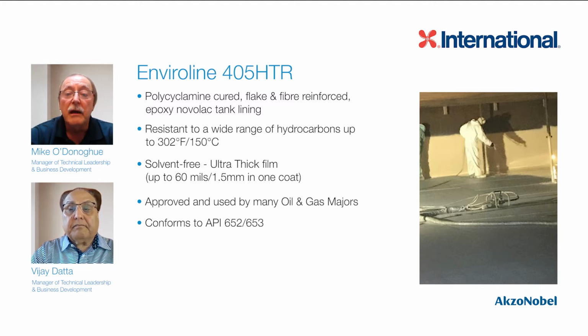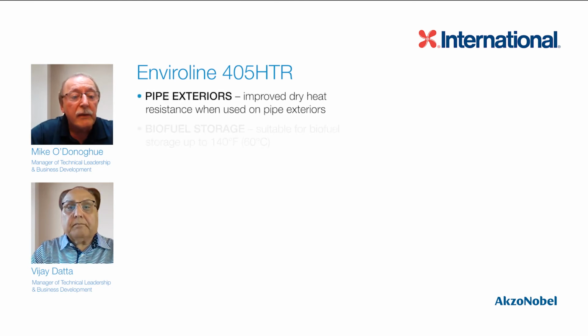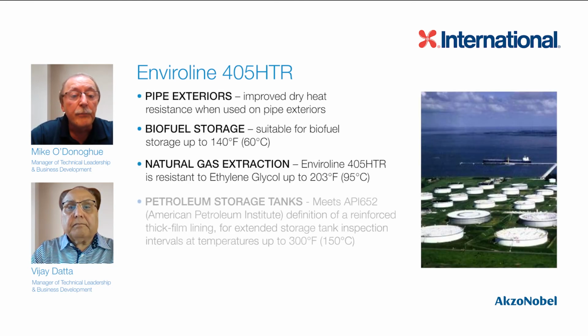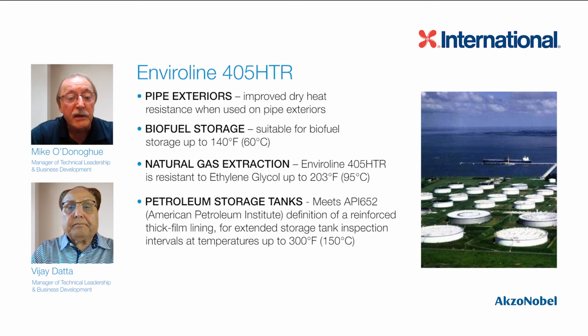So we can get 10 years or thereabouts with inspection intervals being that long, because we've got this conforming to the API. Where are we using the Enviroline 405HTR? Pipe exteriors, biofuel storage, natural gas extraction, and as we mentioned a few moments ago, petroleum storage tanks where we can have large inspection intervals, all while we're maintaining temperatures around about 300 Fahrenheit or thereabouts.